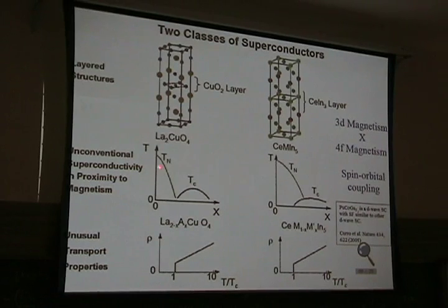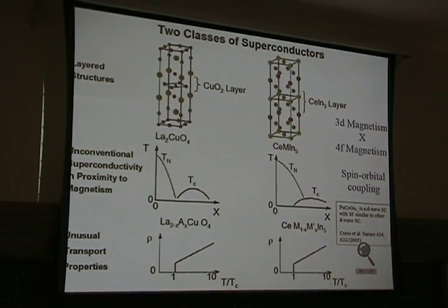In case of high TC, you are really doping the material, right? You have an antiferromagnetic insulator at the end. For the 115 material, they are very good metals all the way in the phase diagram. And you are changing rhodium and cobalt, you are not adding carriers, right? You are just tuning the important microscopic interactions. But they have similarity in the normal state, like I said,